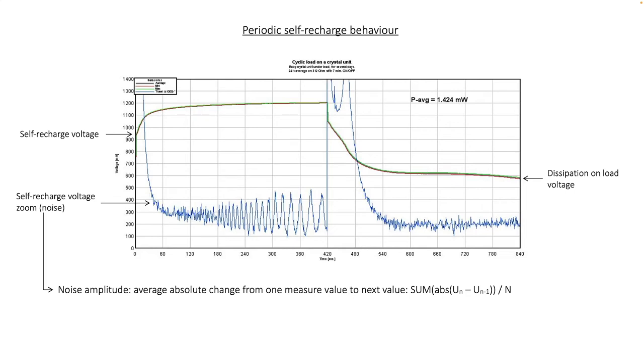Here in this experiment, we do basically the same, but in a shorter time frame of only 7 minutes. And the question behind the experiment was how the self-recharge behavior of the crystal cell works, which was already mentioned before, that after a short circuit for many years, the crystal cell managed to recharge to the previous voltage of 1.2 to 1.5 volts inside of a few minutes. So this experiment should shed some light on that behavior.